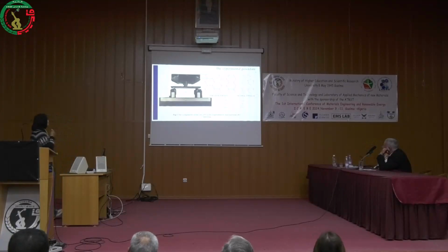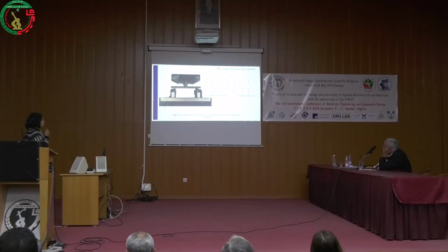So the bending test is conducted in accordance with the ASTM C393 standard and carried out in two different laboratories with three different specimens. And we can see in figure 2 the setup of the flexion machine with the configuration of the core in both the longitudinal direction L and the transverse direction W.